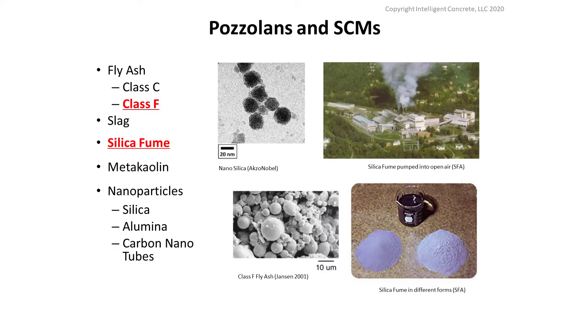The first type is these powdered additives. We call them supplementary cementitious materials and also secondary cementitious materials. They fit under a few different ASTMs: ASTM C618 for our Class C, Class F, and Class N fly ash; then ASTM C989 for our slag, which is much more of a hydraulic material compared to our Class F. After that we've got metakaolin, and more importantly we've got nano silica, which is really the underlying material we're going to focus on to save the world with all the concrete in it.